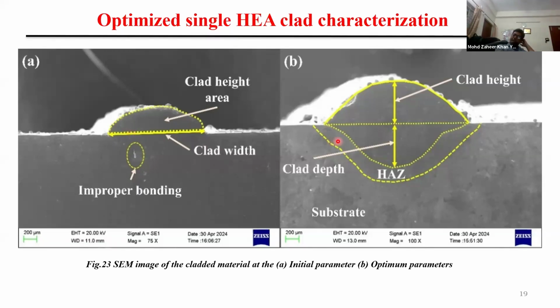Whereas if we want good anchoring, then some substrate material is also going to melt. When the substrate material also melts and the clad material also melts, in this particular clad, they will be mixing. So as you can see, this much is the amount of the deposited material. This is the amount of the substrate material, and therefore they will be thoroughly mixed in the liquid state.